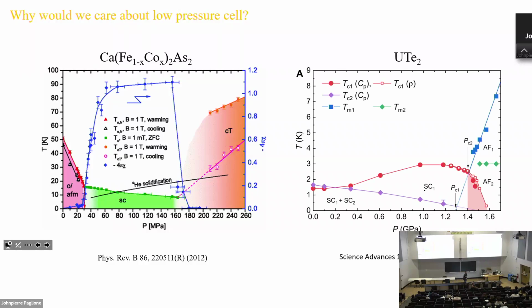My more favorite example, this is uranium ditelluride. And we had the superconductor, we did a pressure study. And this is actually not my work. At the time, there are 3 groups who did the pressure study. And the reason why I put this one, on our phase diagram, the TC linearly goes up. But if you look at this phase diagram from the other group, the TC actually comes down first, then goes up. So we did it too fast.